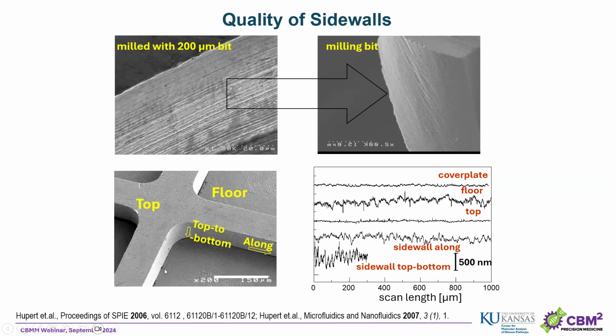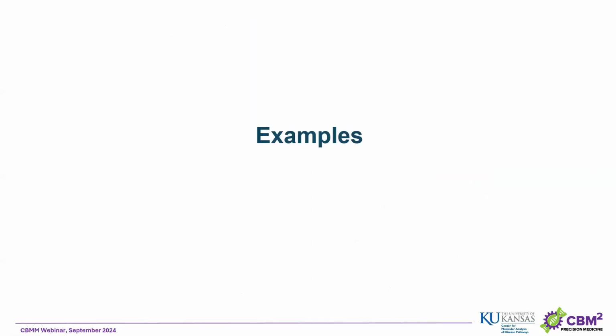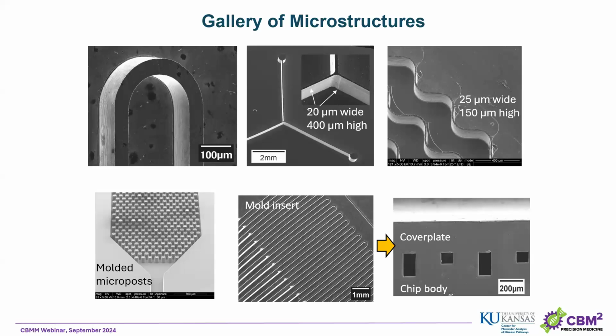And if you do try to measure roughness in different parts of the milled brass, for example, you will see that depending on where on the structure you're measuring, it may be as low as just a few nanometers roughness to as high as a few hundred nanometers roughness if you measure it top to bottom on the sidewall. And just to give you a few examples of how we're using it in real life, this is a gallery of microstructures milled in brass.